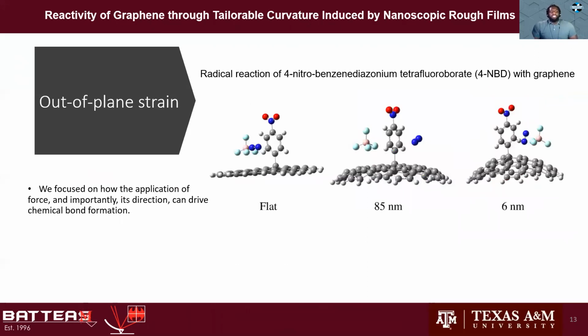And as I mentioned, the product state in our model is the reaction of 4-NBD with graphene, and we visualize the relaxed geometry of the product state of our test system. We use density functional theory and molecular dynamics to calculate these structures and energetics. We used high performance computing from Sandia National Laboratories and the computing cluster at my home university, Texas A&M. And in our work, we experimentally and computationally determined the effect of curvature on the reactivity of graphene.